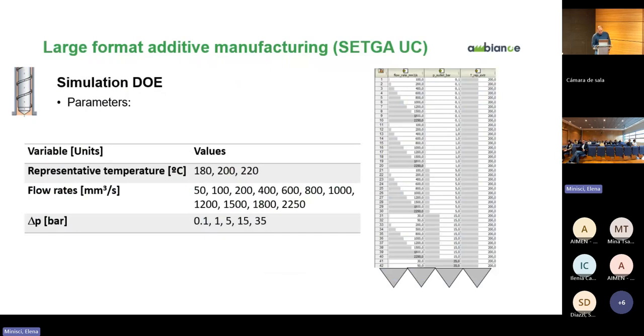Yes. Okay. So next step is to define the ranges. In this case, we have followed the data from the rheology, and we have extended to cover a little bit more of range on temperatures. We have analyzed the full range of flow rates for the extruder, and we have assumed some levels for the pressure loss at the end and in the nozzle in the gap with the layer.